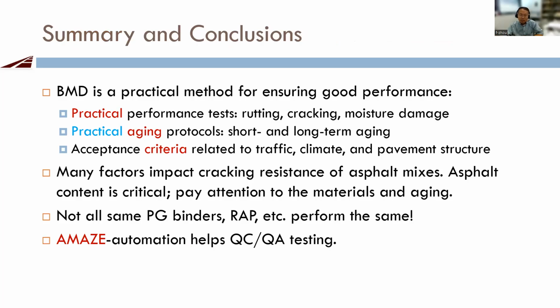BMD is a very practical method for ensuring good performance. You have to look at practical performance tests, look for a practical aging protocol, and establish your acceptance criteria. Many factors impact crack resistance. Asphalt content is always very critical. Also pay attention to your materials and aging. And always remember, not all binders, PMA binders, and RAP perform the same. Do your homework. Also, use performance tests for QC/QA to ensure what you designed is being produced in the field. With that, I thank you very much for your attention.